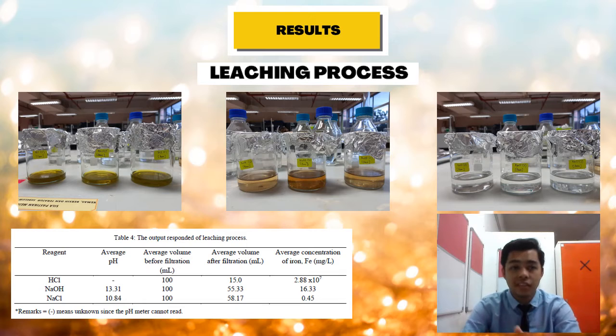For results, these are the three results obtained from the leaching process. These results come from three different reagents which are, from the left, hydrochloric acid, sodium hydroxide, and sodium chloride. Below is the table for the output response of the leaching process. As we can see, hydrochloric acid recovered the most iron from the sample, with a concentration of about 28 milligram per liter, followed by sodium hydroxide and sodium chloride, which averaged 16.33 and 0.45 milligram per liter respectively.